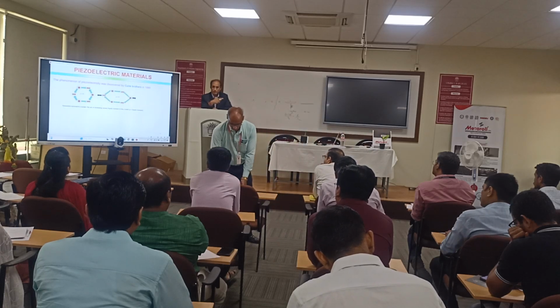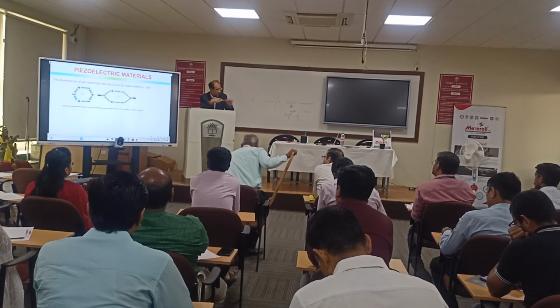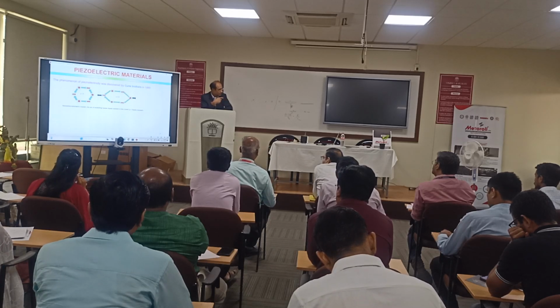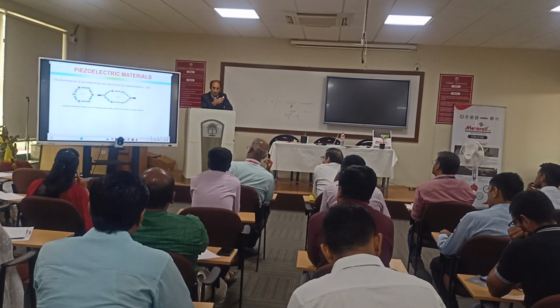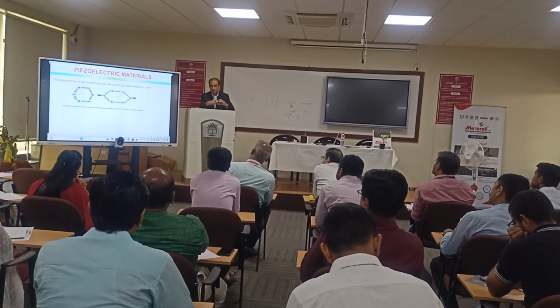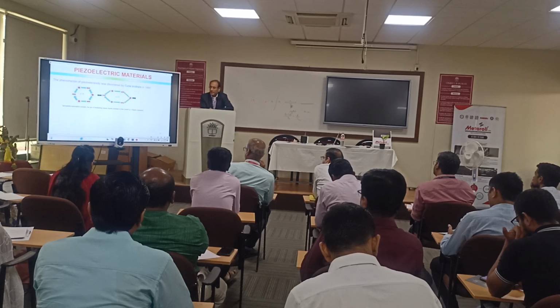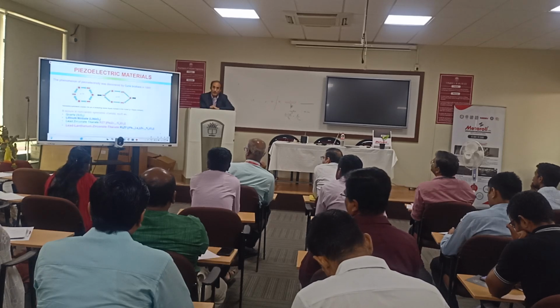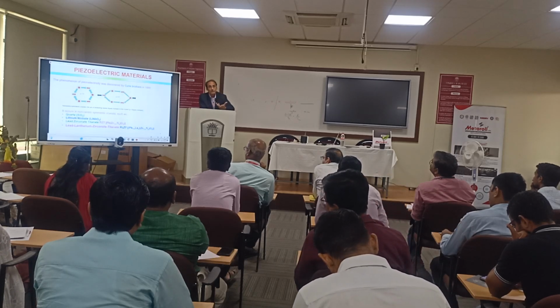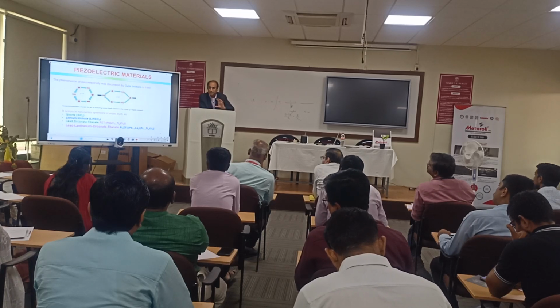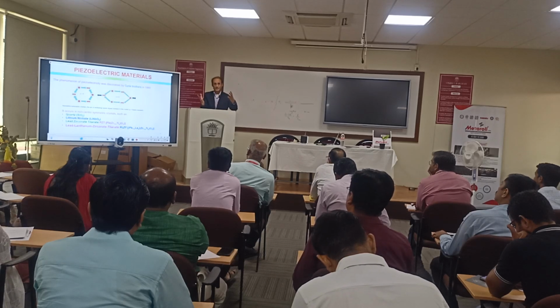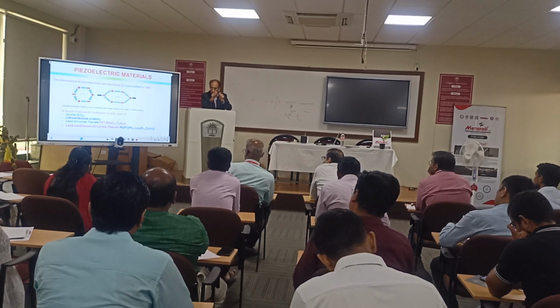So we will focus here on piezoelectric materials. Here I have brought some simple demonstration also. Piezoelectric materials tend to develop internal dipoles if you stretch them, and that leads to accumulation of charges. When charges are there, that means an electric field is produced. So the behavior is just like parallel plate capacitors, where when you apply an electric field, charges are accumulated. Here the charges are accumulated even if you stretch a little.